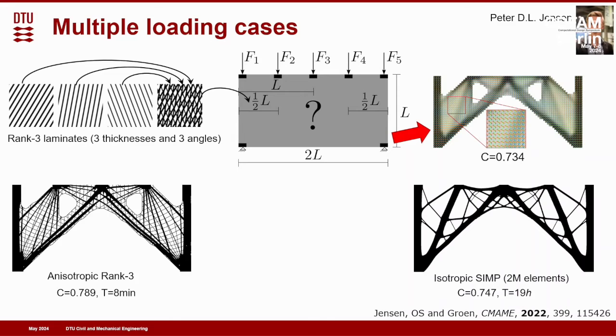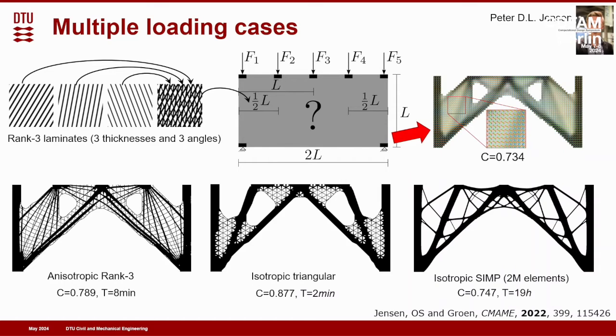Now with the dehomogenization approach, this is just a computer graphics thing. We do the coarse optimization, and then we map the structure to this anisotropic rank 3 structure. We get very similar compliance, just a few percent increase, and we do it within minutes. And finally, if you say, okay, I insist, I want to have a triangular microstructure that we still can grade, well, we could do that also with the dehomogenization approach.